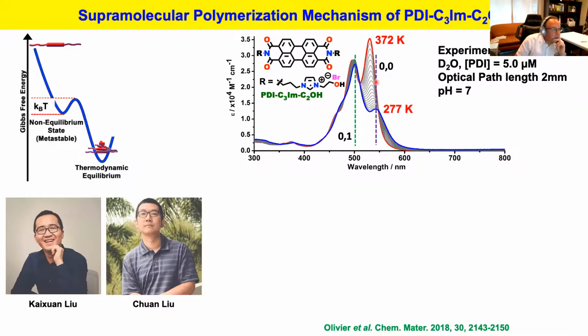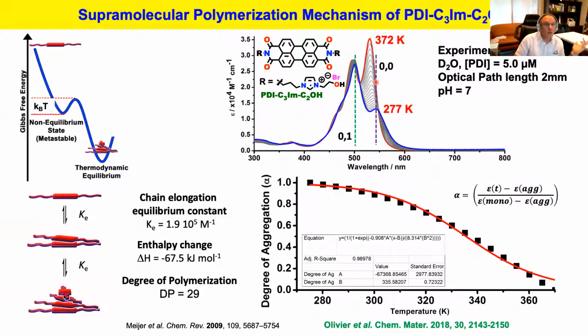Now, what's great about that is that we can start asking questions about the degree of aggregation as a function of temperature. And that's what these little black squares here are showing you. And we can use supramolecular polymerization models that people have pioneered over the last few decades. And so for these specific amphiphilic building blocks that I'm showing you there, the aggregation mechanism is what we call an isodesmic supramolecular polymerization. What it tells us is that there is essentially one elongation constant that is regulating the growth of this aggregate in solution.